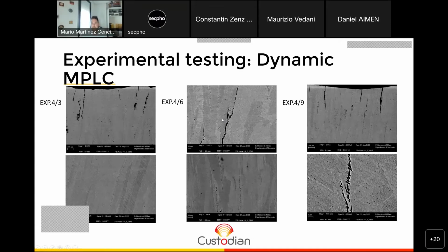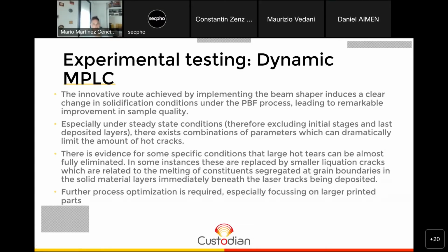So what we can conclude from this first assessment of the process is that the beam shaping induces a clear change in the solidification condition, leading to a remarkable improvement in the sample quality. So especially if we focus on the mid thickness area, we observe that there are processing conditions where hot cracking is dramatically reduced, which is good news. There is evidence for some specific conditions that large hot tears can be almost fully eliminated.